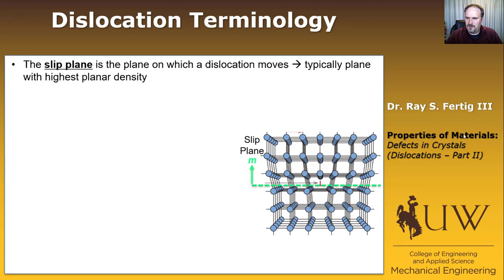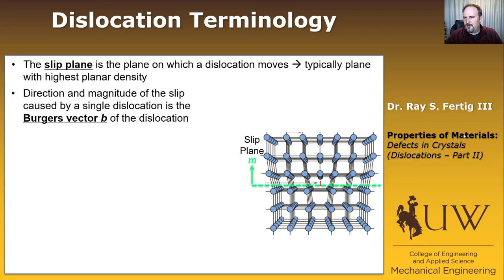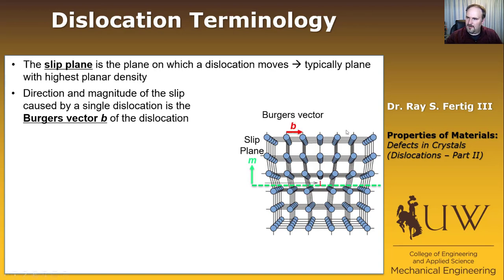There's your slip plane for this problem. The next quantity that describes a dislocation is called the Burgers vector. The Burgers vector is the direction and the magnitude of the slip that is caused by a single dislocation as it moves. In this case, it looks like the distance between just these atoms, because the dislocation is slipping the plane one lattice unit over as it moves.